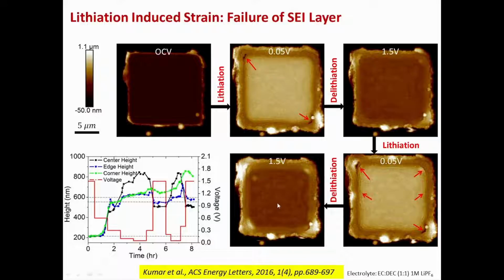As we keep lithiating and delithiating, the cracks become wider and they open up further. So there is a dynamic evolution of these SEI cracks. One thing to note here again is that this whole cycling was done with voltage holds. You can see in the bottom left corner that the electrochemistry of this cell is given.